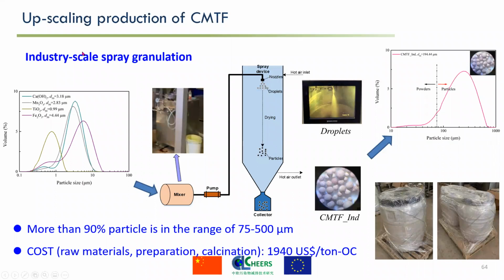In order to upscale the CMTF production, we explored a spray drying process to produce the CMTF at industrial scale, by using conventional raw materials with high purity and moderate price to make a slurry in a mixer. And then we use a spray drying device to form droplets and produce the CMTF particles at the bottom.